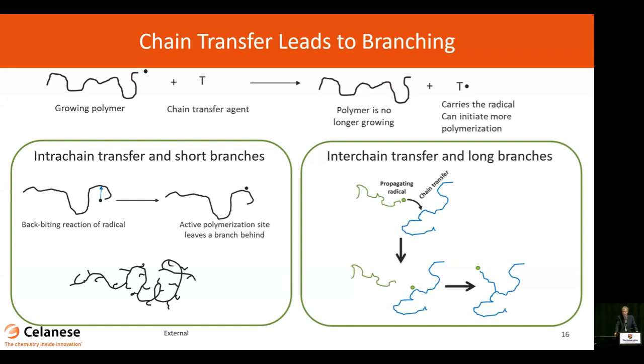This can happen in two forms. First of all, there's intra-chain transfer. In the illustration here, if you have a chain with a growing free radical on the end of it, there's potential for a backbiting reaction. Then you grow from there off of that point and leave behind a short branch in the polymer structure. So there can be quite a lot of short chain branching, and I'll show some examples of roughly how much you get in a polymer in a minute.